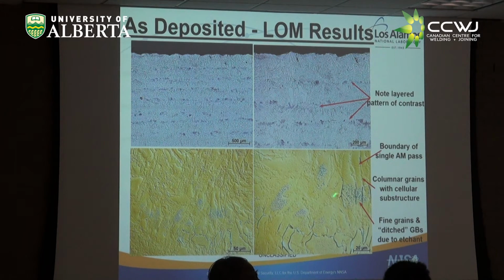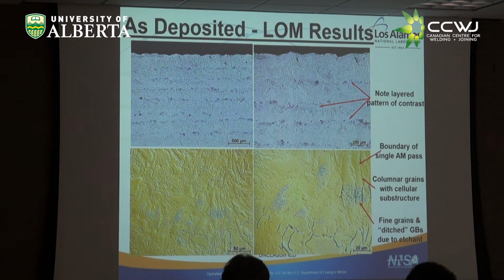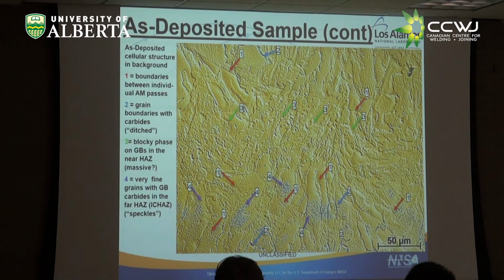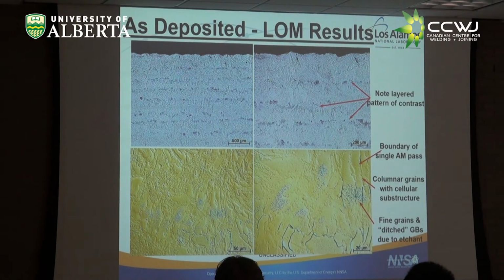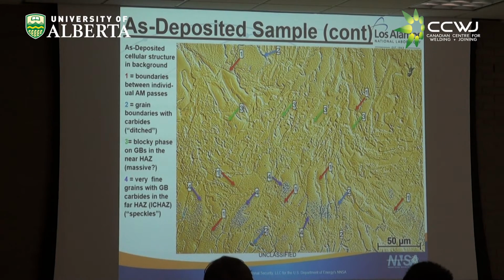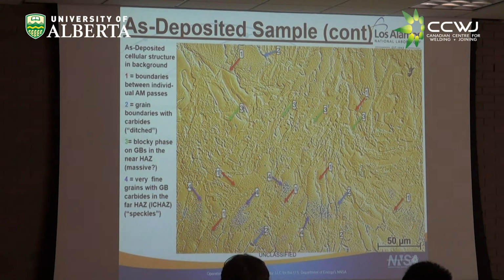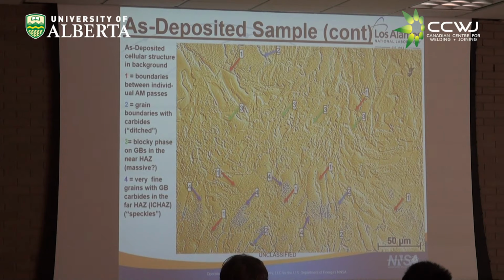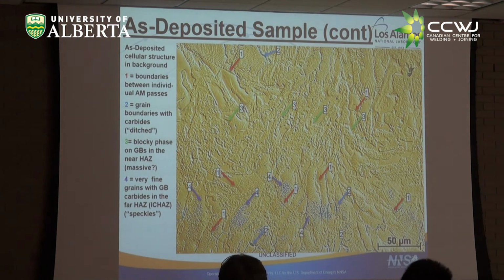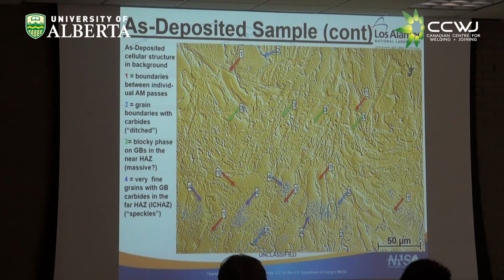You see some columnar grains with cellular microstructure in here. And then you see these little regions here, these fine grains. The guys ended up calling that the speckled region. There are some interesting reasons why that looks speckled that can be seen better here. This is a higher magnification of pretty much one of these regions. We can see several different regions here. So here's a boundary between the given additive passes. There are some grain boundaries here that were decorated with carbides until we etched them. We were not allowed to use picric acid at the lab because they felt it was not safe. And of course, the Department of Energy wants everything to be safe. So we ended up using an etchant that's normally used for stainless steel, and it ended up removing the carbides from the grain boundaries, but I'll show you those at higher mag in a minute.